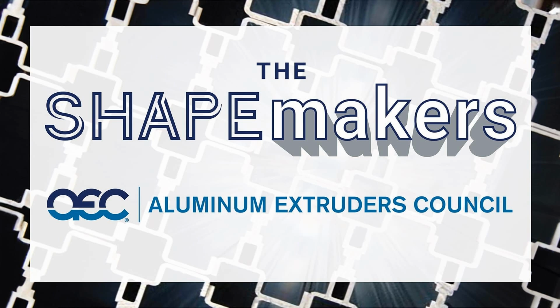First is the collecting of the right raw materials, the virgin aluminum and the aluminum scrap. Second is the melting of those materials together. And the third is filtering the melt and pouring it into the molds, typically 24-foot long. And at Tower, we cast 6, 7, 8, 9, 10, and 12-inch diameters, and then you let the logs solidify. The final step is the homogenizing of the logs, which is heating them in an oven up to about 1050 to 1060 degrees Fahrenheit to get the correct and uniform grain structure.